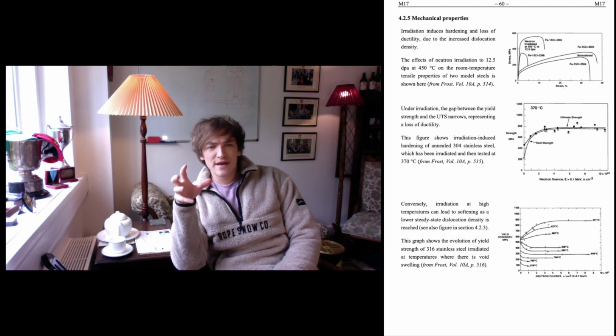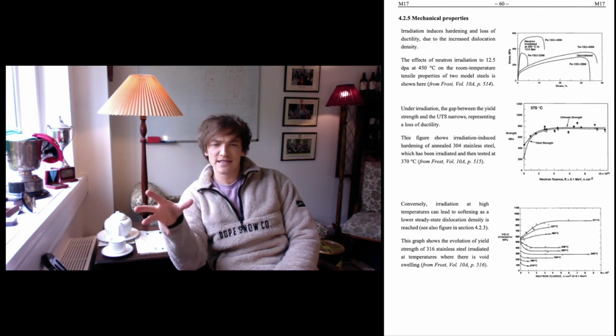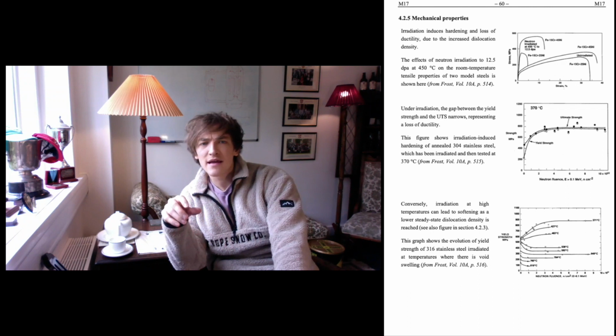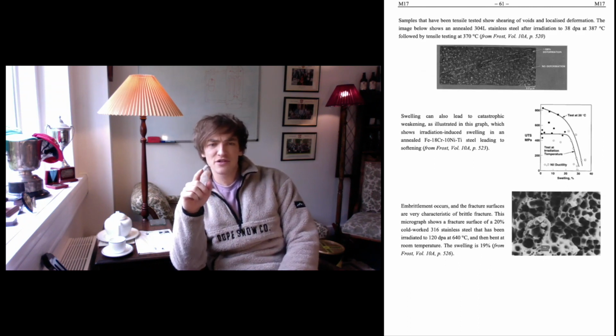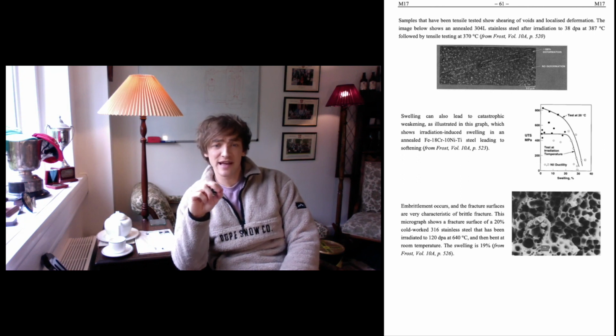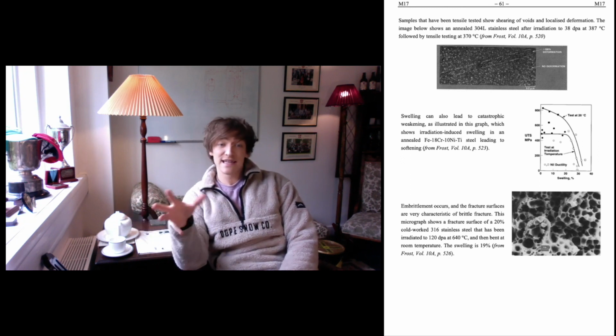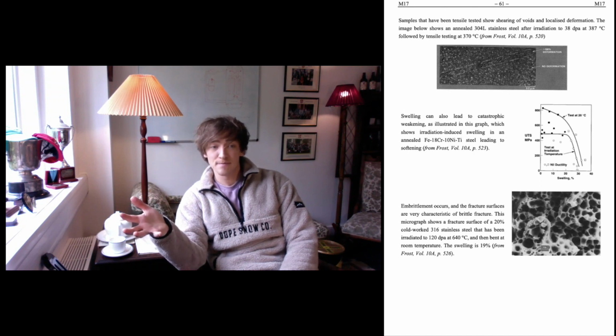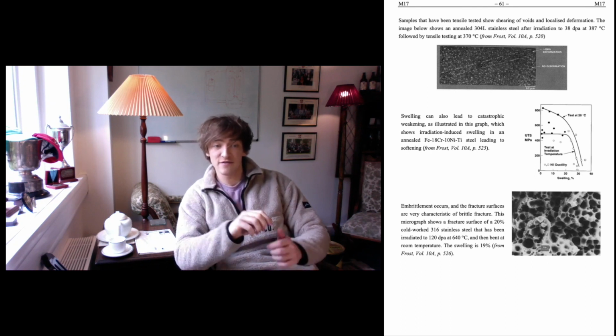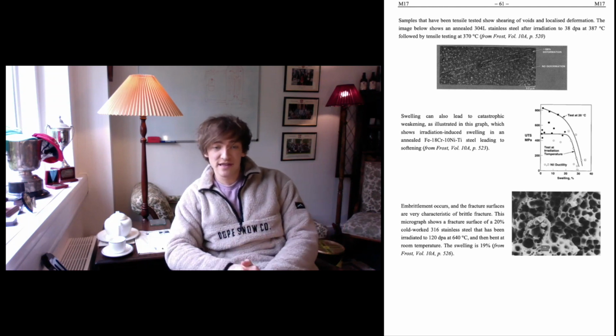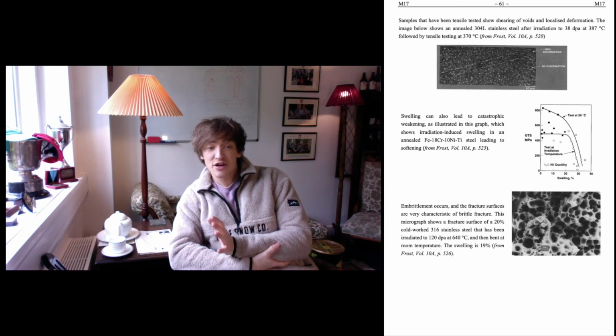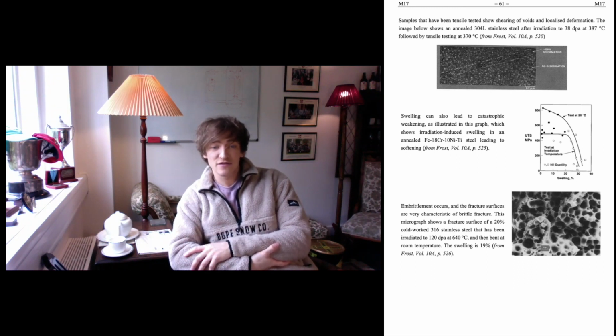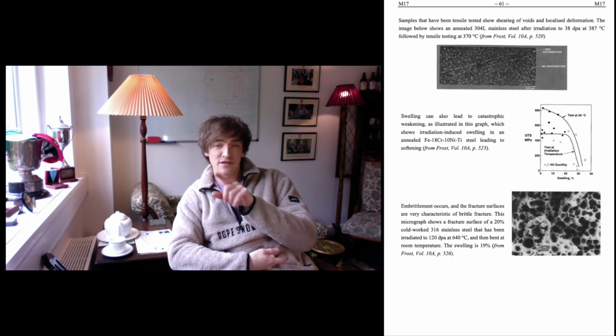Now, when it comes to the fracturing of such irradiated stainless steels, you may see something like this. The image at the top here of page 61 shows a heavily irradiated 304 stainless steel sample with a shear band across the centre, within which voids have been sheared. Now, of course, swelling leads to catastrophic weakening, eventually causing fracture. And that's shown in the following two graphs. The lower image showing the fracture surface of a brittle stainless steel 316, which was irradiated at 640 degrees Celsius and then bent at room temperature. And it just shows that you get this loss of ductility. So you do get catastrophic failure, and you get the shearing of those voids, which you can see along that deformation band.